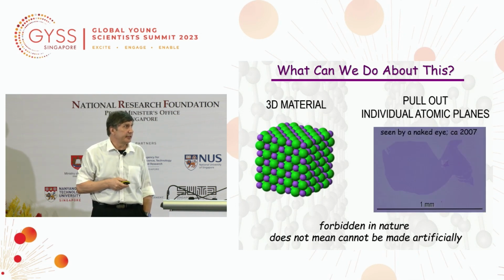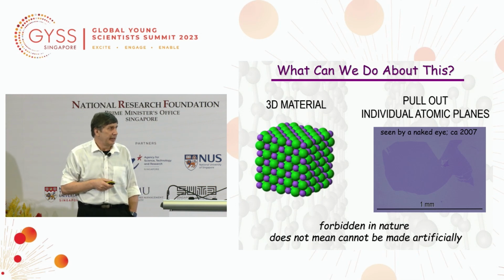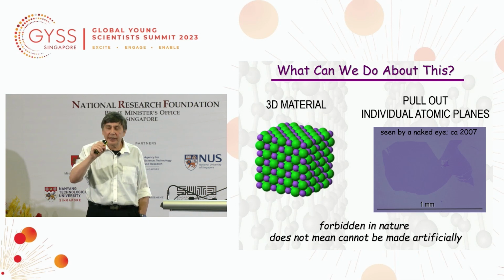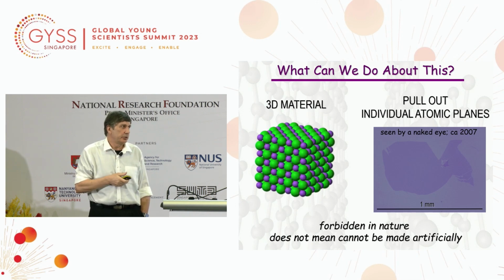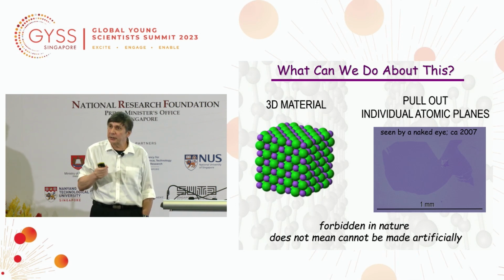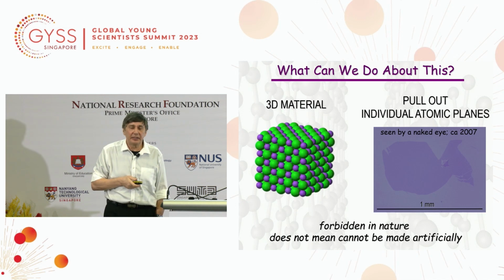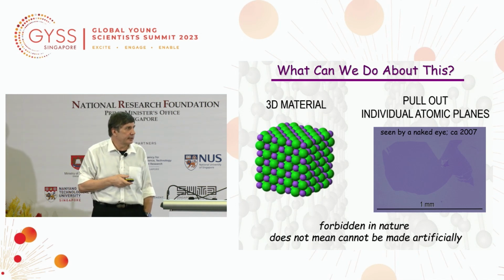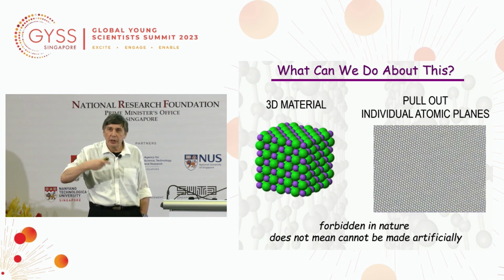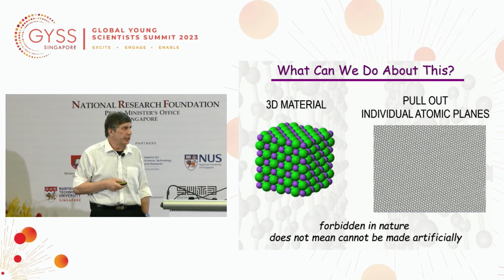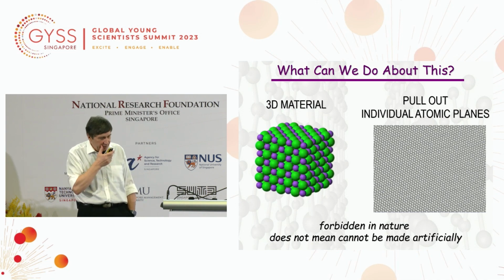So this is an example of a photograph from about 15 years ago, a 1 millimeter monolayer of carbon, one atom thick carbon crystal, which is seen here. You can see it by naked eye. Also quite a surprise, because with one atom you would think it would be the thinnest possible film you can imagine, and you expect it to be completely transparent, yet you can still visualize it. Of course, you can use all these powerful modern techniques, including transmission electron microscopy, and make sure that it's indeed a crystal of carbon atoms. And this is a real photograph there.